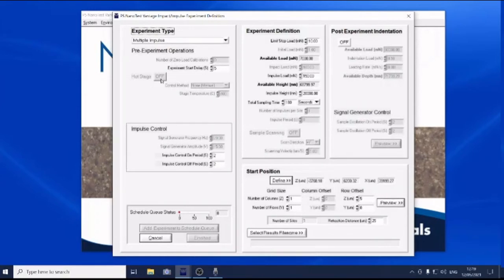So we can define various important elements of our test. We won't go through everything in detail now, but probably the most important element is the load that we're going to use. We already know a little bit about this sample, and we know that 1,500 millinewtons, 1.5 newtons, should lead us to some quite nice failure events. Another important thing is how long we're in contact with the sample surface and how long the probe is out of contact with the sample surface.